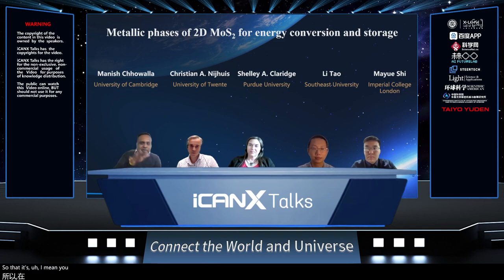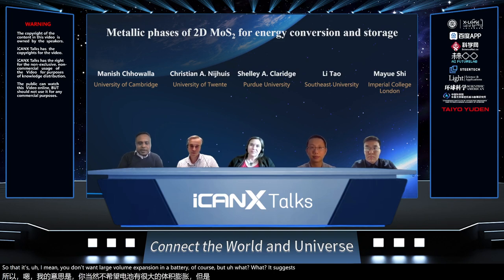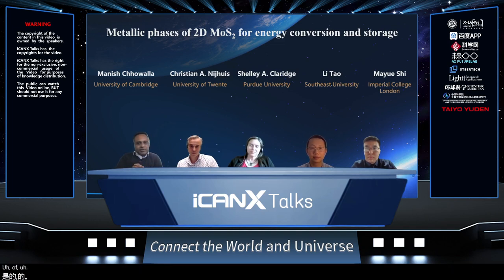You don't want large volume expansion in a battery, of course, but what it suggests is that they're very malleable in terms of allowing ions to come in and out of their structure. So we found that just by natural processing, it seems to be the right type of structure that allows these processes to occur. That's fantastic. Thanks so much.